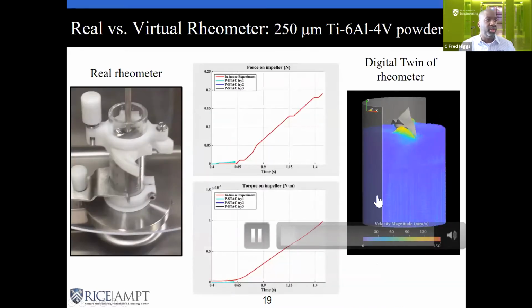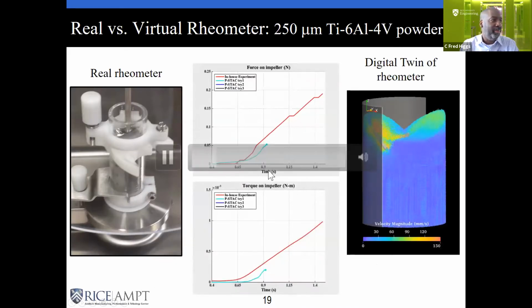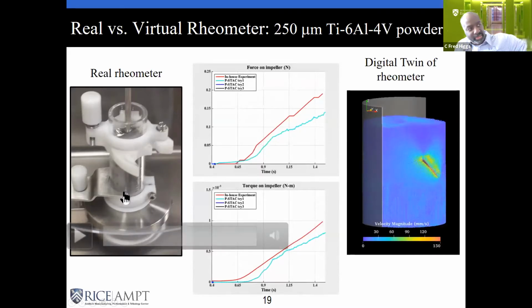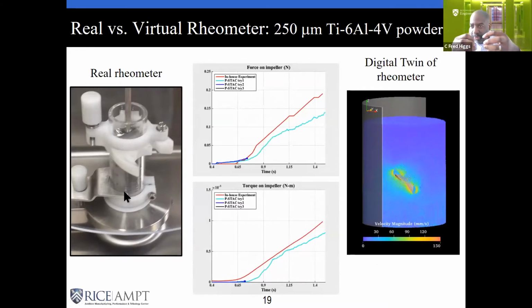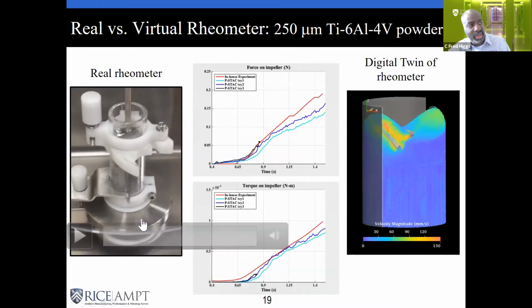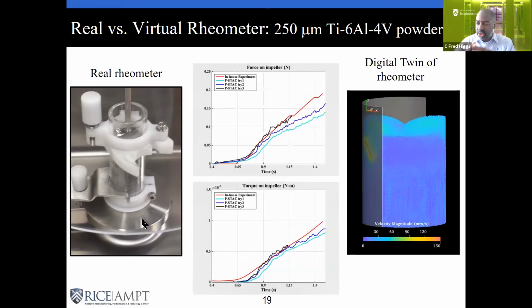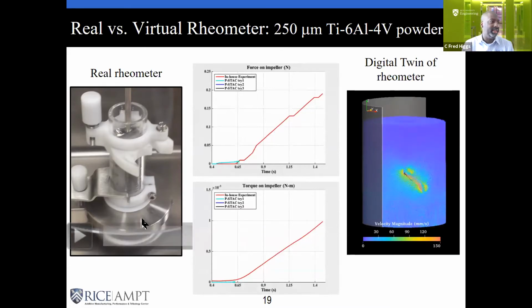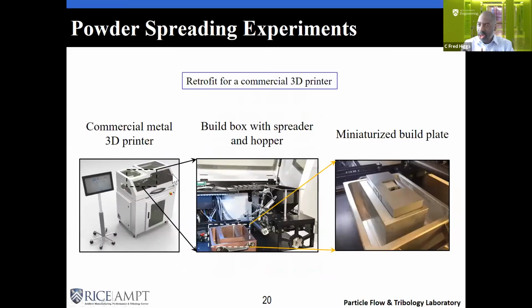So we end up here with a digital twin of our rheometer here. And basically, the red curve comes from this physical rheometer, and these other curves that are being generated are just tuning the micro properties of the powders to get them to match the energy signature of that actual physical rheometer. Once we get closer, you can see these iterations are getting closer and closer. Once we get closer to that red line, you now have what's called a digital twin of the powder there. And now you can use it in other simulations, like 3D printing simulations. But we are always validating these things, and then we can get lost in having fun and optimizing in the virtual world or the computational world.